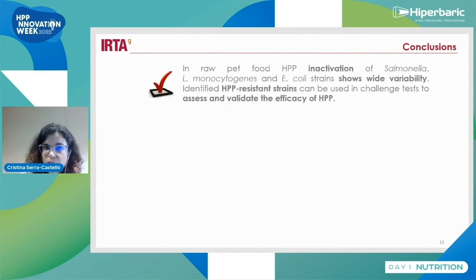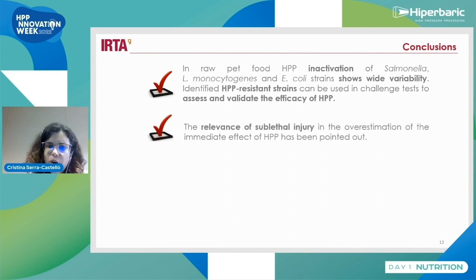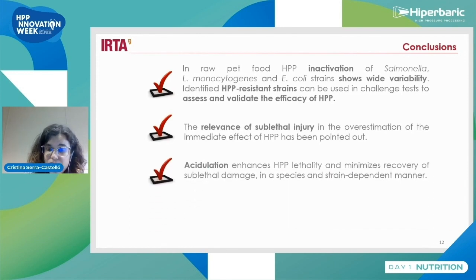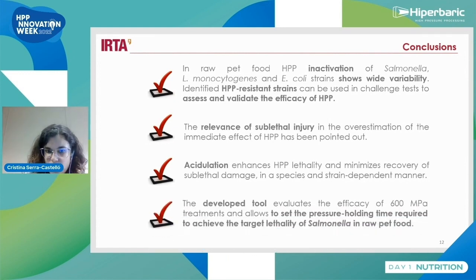Thus, the conclusion of this study was that in raw pet food, high pressure processing inactivation of Salmonella, Listeria monocytogenes, and Escherichia coli strains shows wide variability. Identified high pressure processing resistant strains can be used in challenge tests to assess and validate the efficacy of high pressure processing. Moreover, we put forward the relevance of sublethal injury in the overestimation of the immediate effect of high pressure processing. Also, acidulation enhances high pressure processing lethality and minimizes recovery of sublethal damage in a species and strain-dependent manner. And also, we developed a tool to evaluate the efficacy of 600 megapascal treatments that allows setting the pressure holding time required to achieve the target lethality of Salmonella in raw pet food.